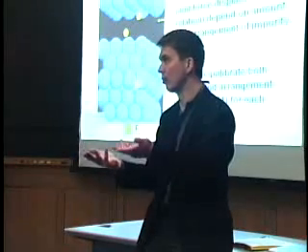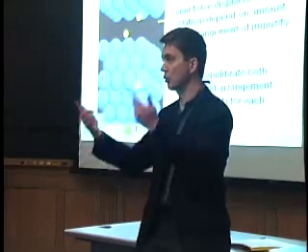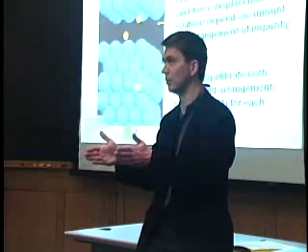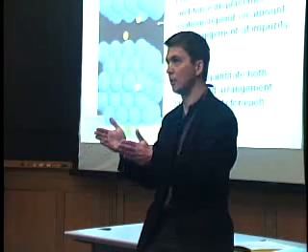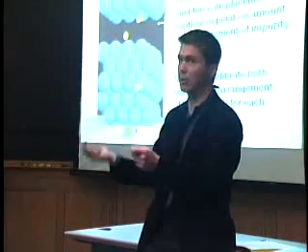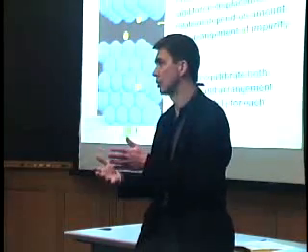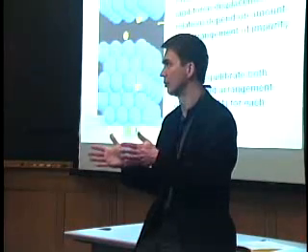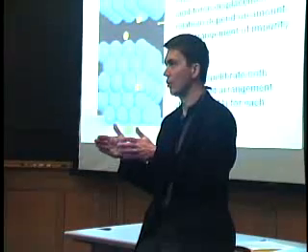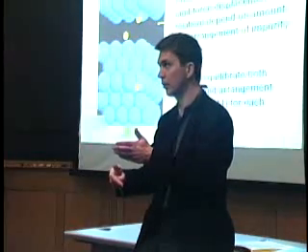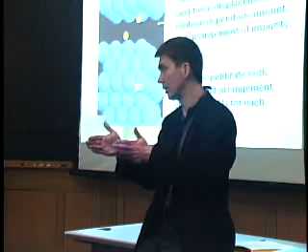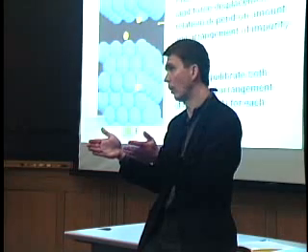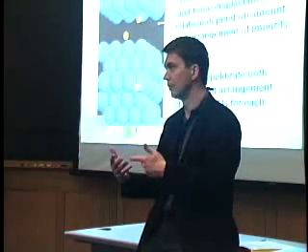Because as that impurity equilibrates, not only its structure, but also its composition, because segregation to those surfaces is an open system problem. The concentration there is not fixed because it comes from the bulk or from a gas phase. So it's actually a grand canonical problem. It's a constant chemical potential problem rather than a constant composition problem. So the hard problem is that not only do you have to arrange the impurities in the most stable way, because that's going to determine the energy and therefore the force it requires to open up those planes, but you also need to equilibrate the amount of impurity in that crack.